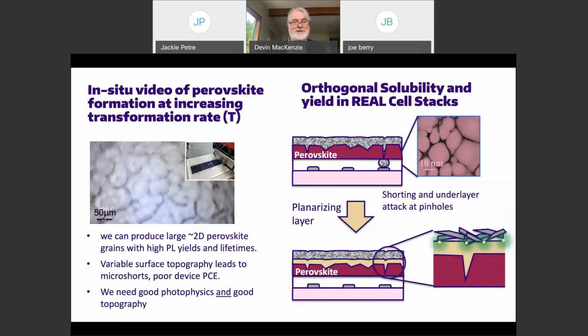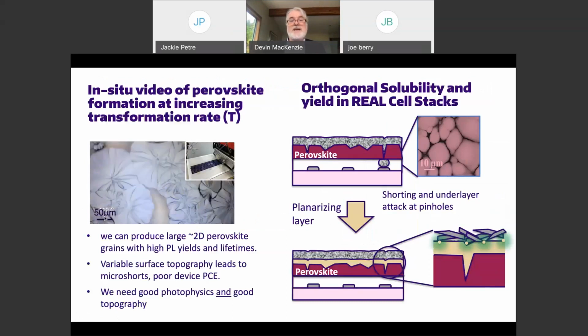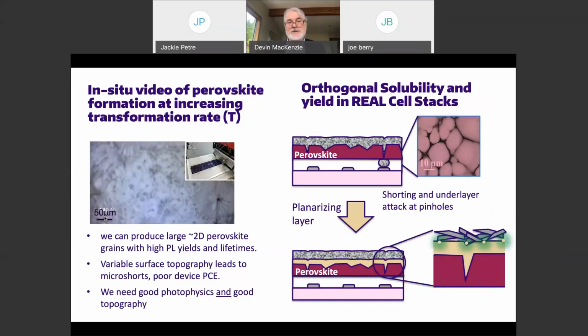That's important because grains are, in our experience, directly related to yield. Here's a quick little video. This is a sequence of perovskite growth at different substrate temperatures, and you can see the rate of growth increasing and the grain size going down and down as we increase that transformation rate. Now follows the spin coating version. Spin coating is sort of hyper quenched, a really fast transformation rate, and it leads to much finer grains. But the real story here is we're growing 50 micron grains that are relatively two-dimensional. These are not the crazy needles that happen otherwise. But ultimately, that's still a problem.